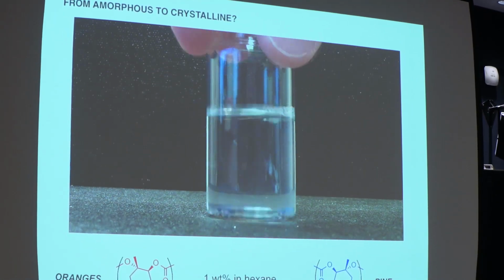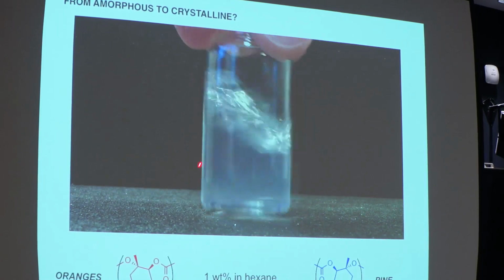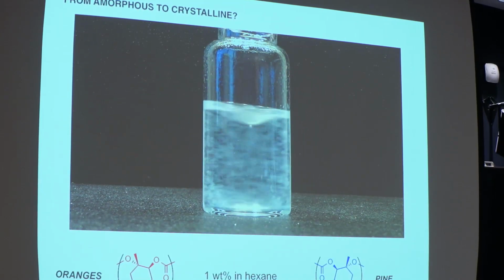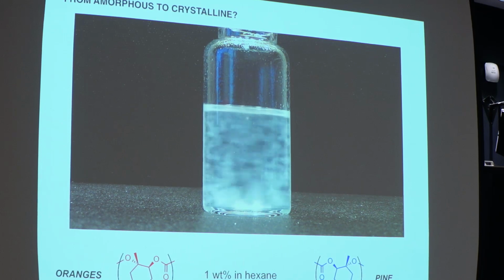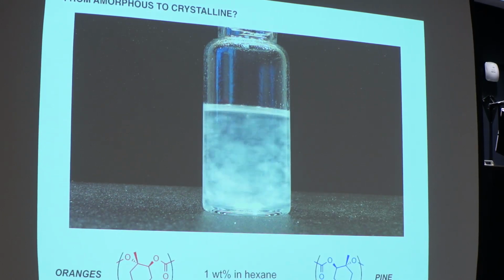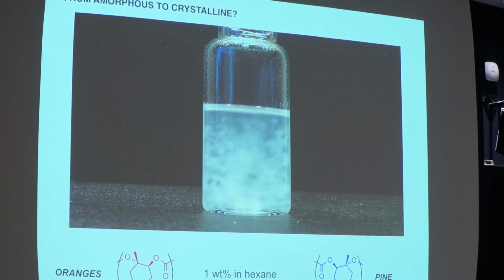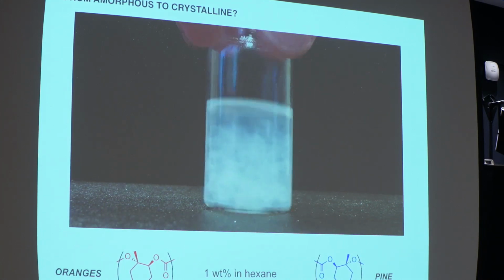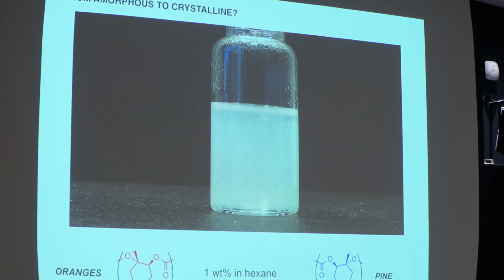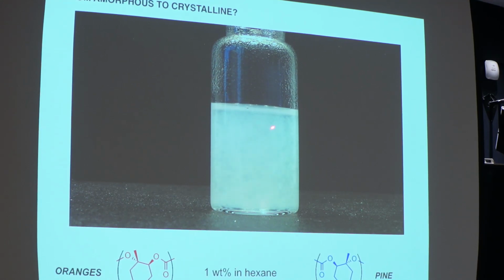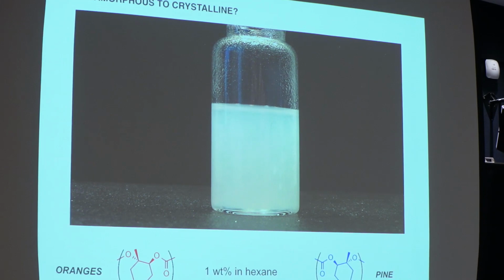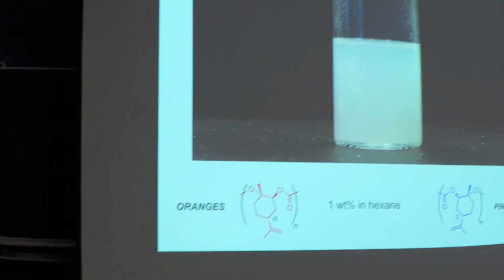So the one from oranges and the one from pine trees. And you can see that we've got a white precipitate. And these are 1%, so very dilute solutions. They're not even viscous. Until you mix both enantiomers together and give one little more swirl, you can kind of see that little bubble. It kind of gels up. And at this point, this could just be that they somehow crashed out together. But we were optimistic that these might actually have co-crystallized.